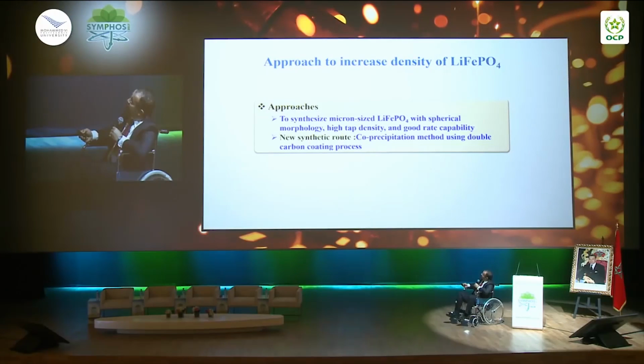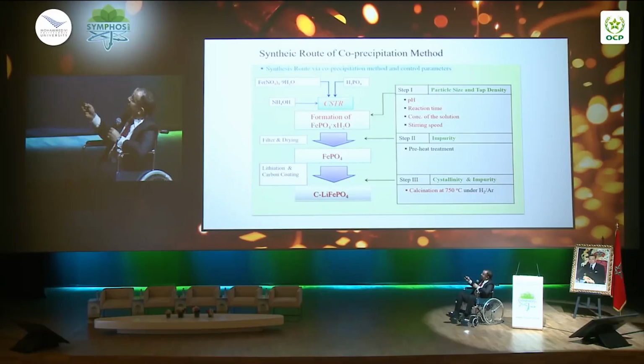It's a co-precipitation. We want to synthesize micron-size iron phosphate. If you do that, obviously the diffusion pathway becomes very long and the performance will drop. But we also want to put clever nanopores through the particle, and I will explain why it's important. To make this material, this is a process that uses phosphoric acid. I know that OCP is the largest producer of phosphoric acid, so there is an opportunity with this. And you use a cheap iron 3 nitrate material. You put it in a reactor, you use a chelating agent and co-precipitating agent, and you form this phase here, and basically you dry it, you filter it, you form FePO4, and then you lithiate it. And then you do the carbon coating using the process I showed you.